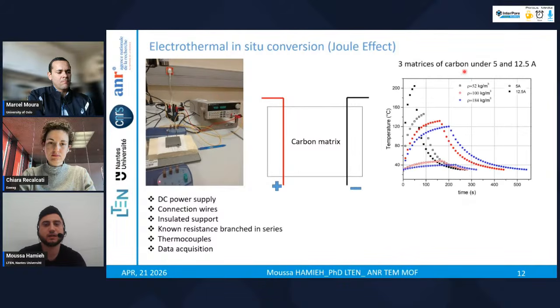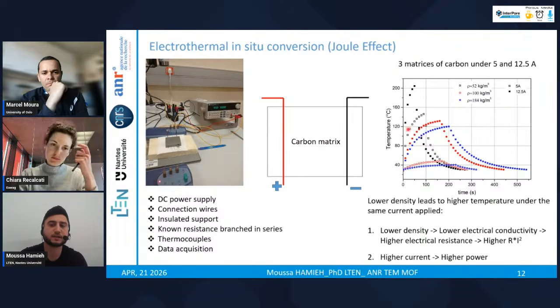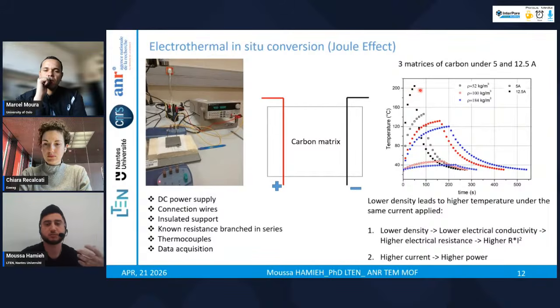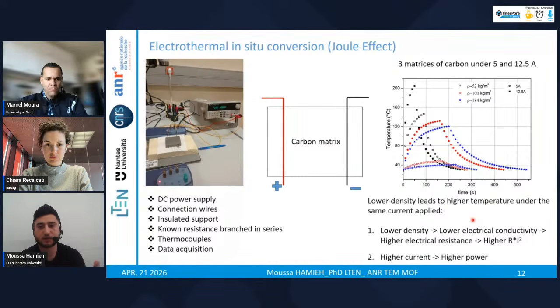We tested here three densities of carbon matrix, from 52 to 184 kilograms per meter cube, under two different currents, 5 and 12.5 amperes. We see that lower density leads to higher temperature, because lower density means lower electrical conductivity and so high electrical resistance, and therefore with high electrical resistance we have more heat generated through the Joule effect. And also, as expected, when increasing the current, we increase the energy from the Joule effect, so we reach higher temperature. So overall, both density and current strongly influence the heating behavior of the carbon matrix material.